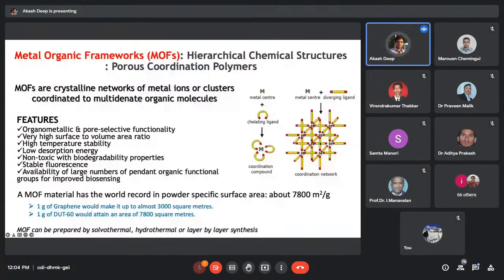The features of such types of structures are listed here. They are organometallic compounds and they have pore selective functionality. The explanation of this pore selective functionality is that we can have different diverging ligands with different lengths here. If we change this length or the geometry of this diverging ligand, then we achieve different pore sizes. You can see that the window here has a particular pore size, but by changing the length of this ligand, we can make a selective pore size of this framework.